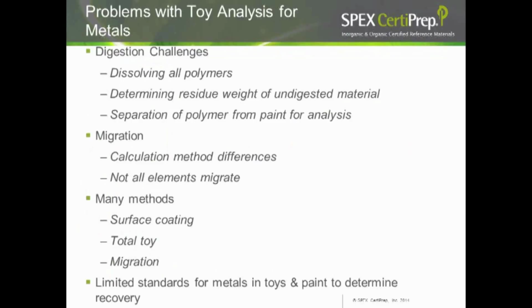So, some of the challenges that we found with analyzing toys for metals. There were digestion challenges. It's very difficult to predict whether all the polymers are going to dissolve, especially when the polymers are from different sources or contain different additives, which sometimes changes the chemical composition and makes it more difficult to digest. Also, determining the residual weight of any undigested material can be a problem and add a source of error to the calculations. And it is very, very difficult sometimes to separate the polymer from the paint for analysis. It was difficult when scraping the paint off not to get the underlying polymer and therefore add polymer into your total sample weight. And as I said before, since we had a limited amount of paint on our sample, sometimes trying to collect enough paint to get a result was a difficult process.